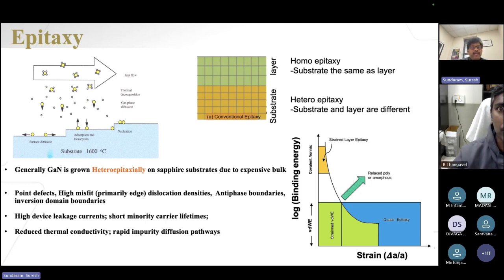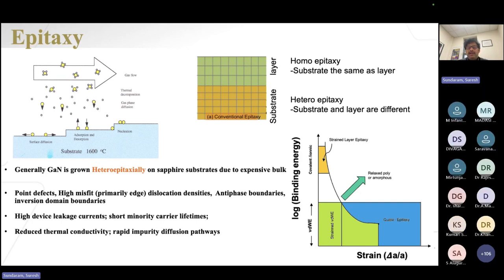There are a lot of mechanisms, for example, surface diffusion, adsorption and desorption. Once we have stable nucleation, it grows to form a stable layer. Generally, gallium nitride or III-nitride is grown heteroepitaxially on sapphire substrates due to the expense of bulk. Bulk substrates are available, but very expensive because the process to get bulk crystals is very expensive. And we cannot have very large substrates. We can have 2-inch max.